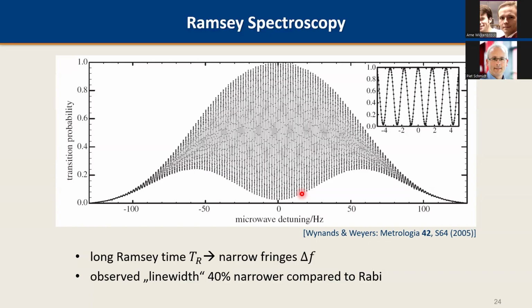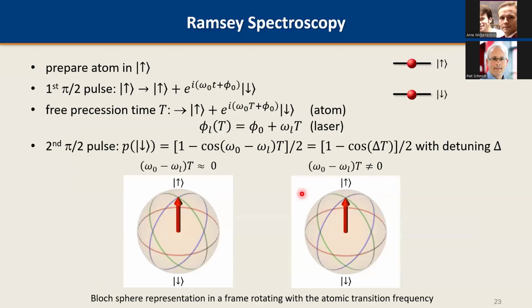And the reason behind the decay is dephasing. Is that correct? It's just the spectral bandwidth that you can address in these pulses. So you run out of, if the detuning becomes too long, then, now I need to think where this is coming from in the end. I'm not sure if it's dephasing. I think it's if you're detuned with your laser too far and the pulse is not short enough, then you cannot actually excite it. You do not bring it all the way to the equator any longer.